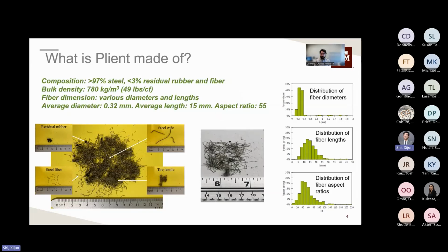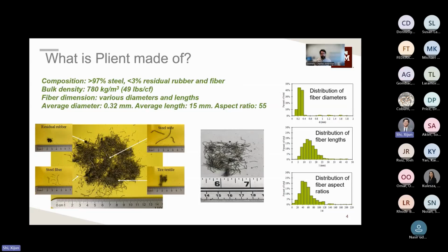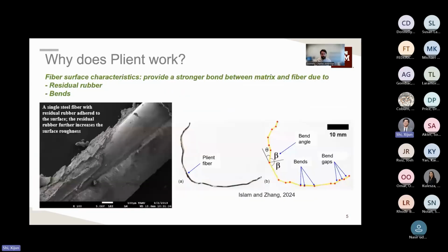Something that's unique about Plient fibers compared to a manufactured steel fiber is that because of the recycling process, as opposed to a uniform length and diameter of the fibers, there's a distribution of the lengths, diameters, and therefore the aspect ratios. So Plient fibers are an effective fiber solution for two key reasons, and both of them have to do with the interface between the fiber itself and the concrete or the cement matrix.